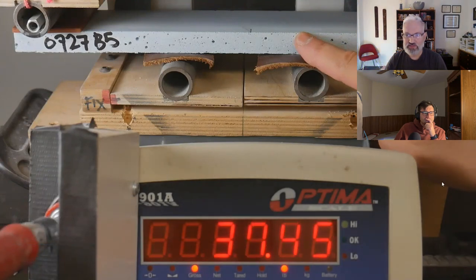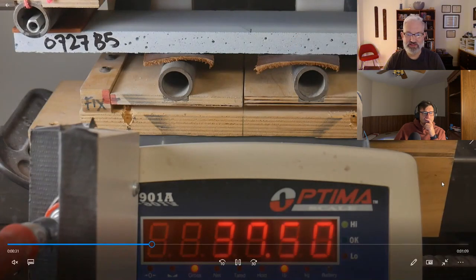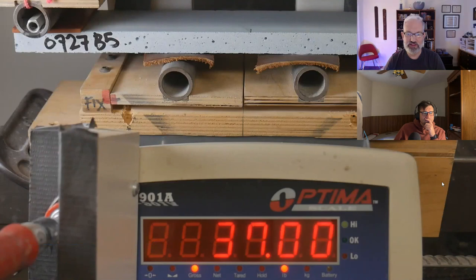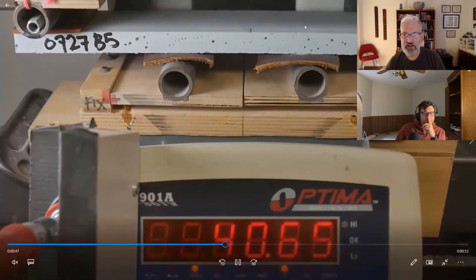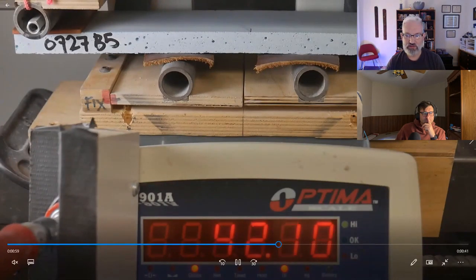Now watch what happens. It's already cracked. Look at the load. It'll go up and down a little bit as the concrete engages the fibers differentially, and this is what you want to have happen. It went down, and again it's going up. Now that crack's a little bit more visible. And when you relax it, you can't see it anymore. You might see more cracks happen. We're close to failure, but we're not at failure.